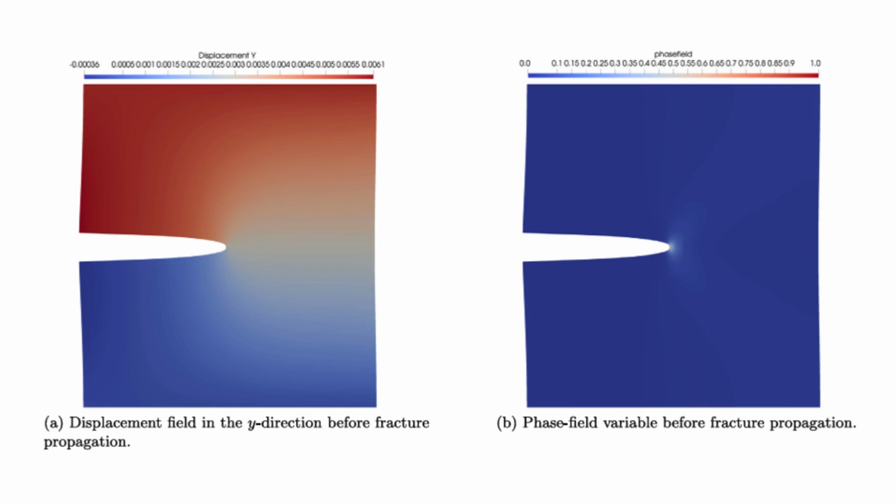We also saw how sensitive the result was to the user guessing the right time step, delta t. Right, you needed tiny steps for accuracy at the critical point. So the next level isn't just a faster solver, it's smarter computation. Things like adaptive time stepping, where the code automatically takes smaller steps only when needed during rapid changes and larger steps otherwise. Let the code figure out the step size dynamically. Exactly. And potentially adaptive mesh refinement, even though PFM avoids remeshing. You might still want a finer grid temporarily right around the crack tip where things are complex, and coarser elsewhere to save effort. Let the simulation focus its computational power geographically as well as temporally.